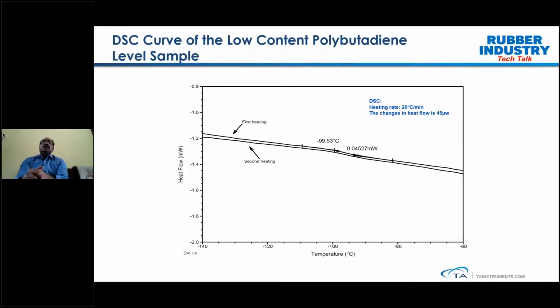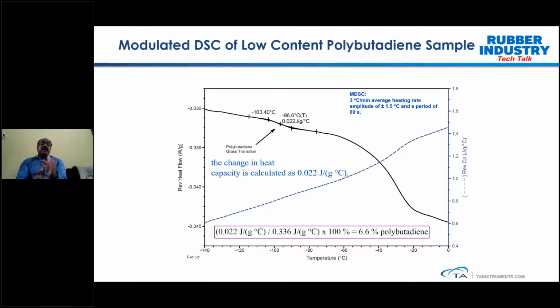Now, when you come to the low content polybutadiene, because this is an unknown sample, we want to understand how much polybutadiene is present in this particular polymer. When you look at that, it is very difficult, nearly impossible, to detect the glass transition temperature which corresponds to the polybutadiene. So we test the same samples in modulated DSC, and now you can clearly plot the reversible heat flow, which is going to show the glass transition of the polybutadiene. We are plotting here the reversible heat flow and reversible Cp against temperature.